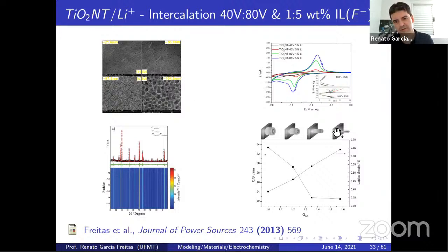As soon as we decrease the diameter of the nanotubes, we observe that the crystal size decreases as well, from 34 nanometers to 22, like here, and the border of the grains increases. As a result, we increase the lattice strain from 0.35 up to 0.7. So if we increase the lattice strain, we can tune its effect, and as a result, we can tune the reversibility of the ability of lithium to get inside the nanotube and get outside the nanotube, because here the cathodic charge divided by anodic values is 1.6. So again, some structural and electronic properties result in some modifications in electronic properties like energy conversion or storage in this case.